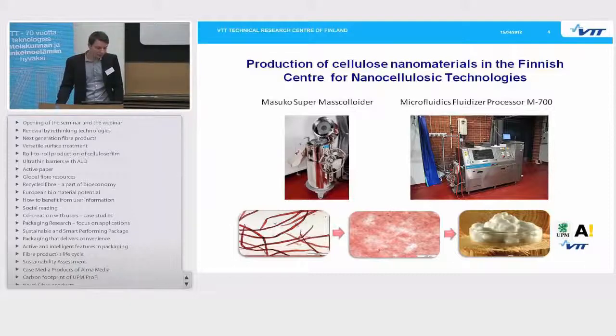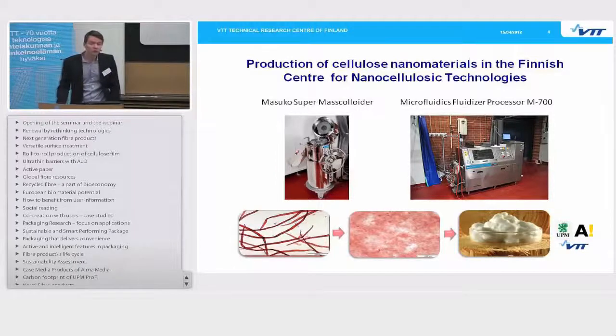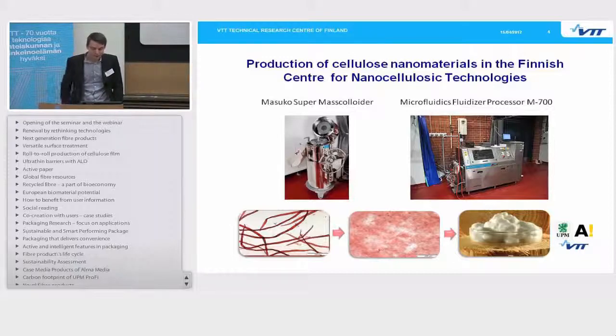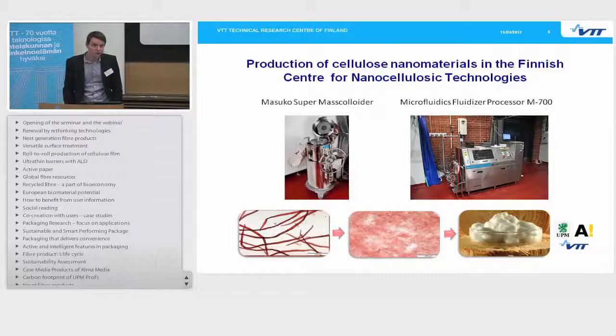If you look at the pictures below, on the left-hand side you will see untreated fibers. In the middle picture, those fibers have been treated with the Masuko Grinder — the scale on both pictures is the same, so you can really see the change happening to the fibers. On the right-hand side there is finished nanocellulose at about 2% consistency, and you can see how gel-like that structure really is.